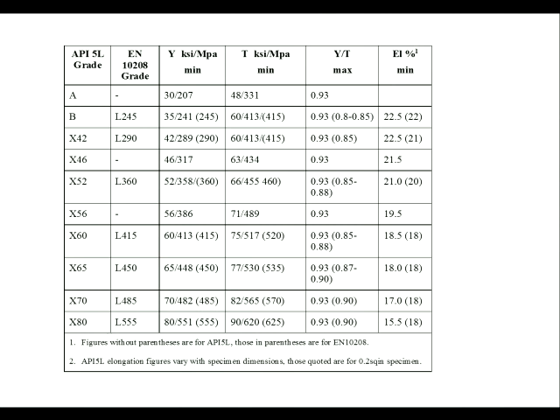So if you take grade B, for instance, you can see that 241 has gone to 245, 413 has gone to 415, 0.93 has been reduced to 0.85, or 0.8 to 0.85 in most cases. But they're still the same steels. So you need to know, as I say, if you're looking at materials, which standards is the company working to? And just make sure you do all that.